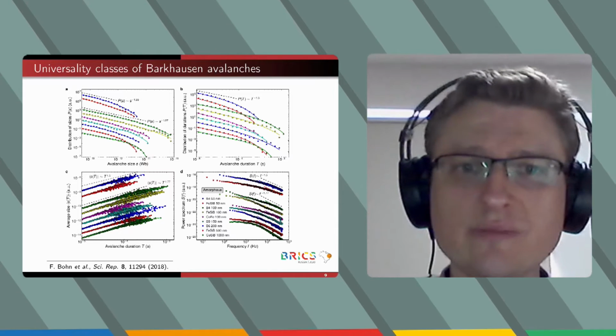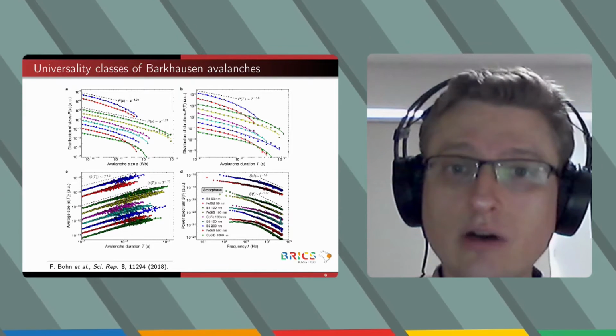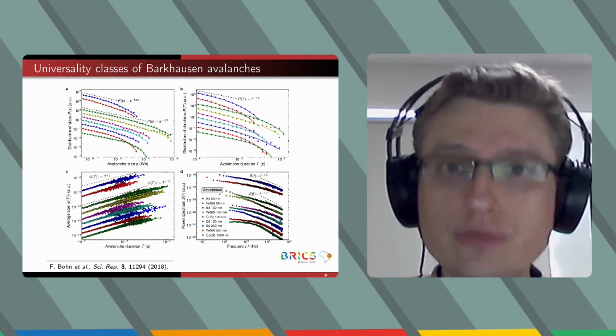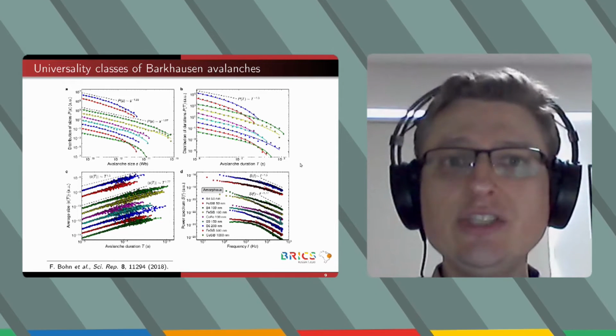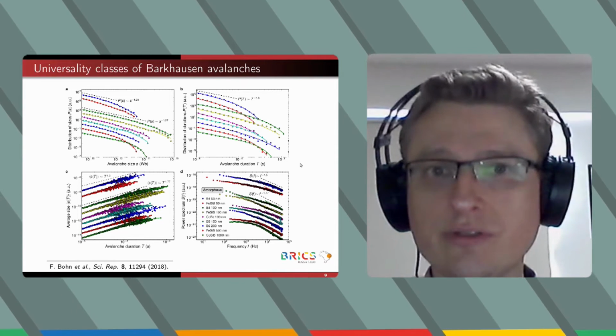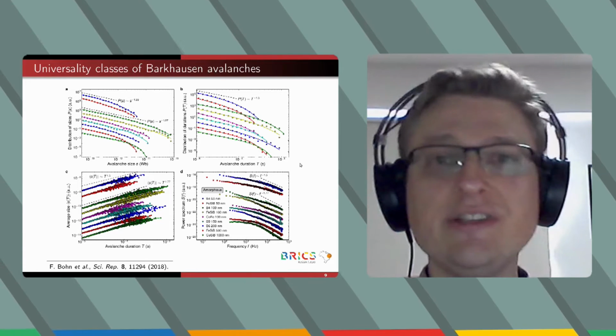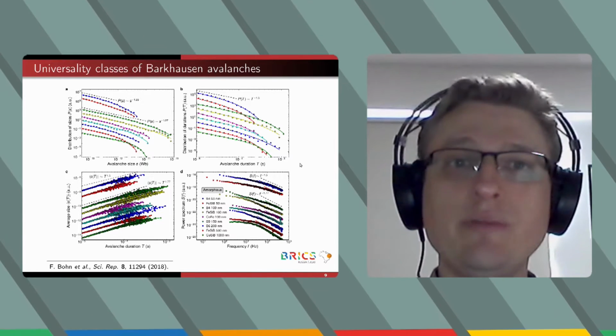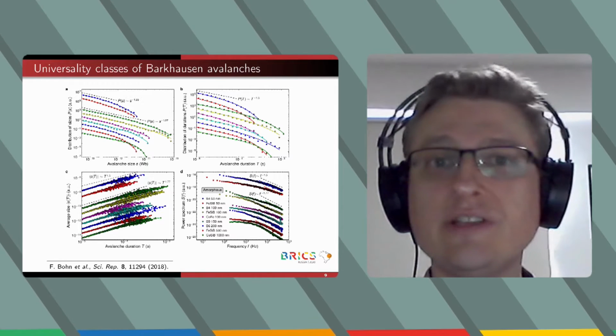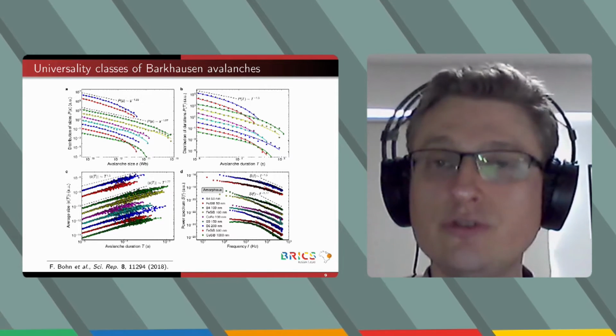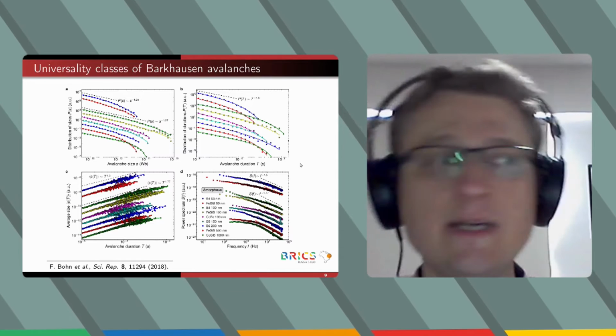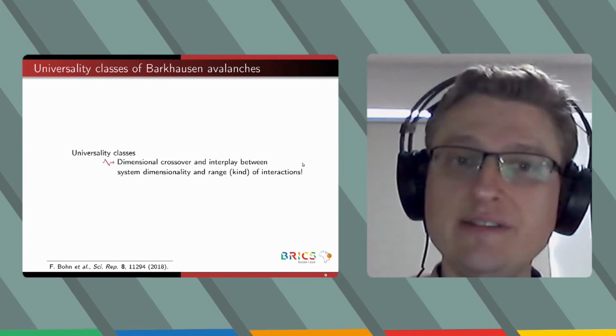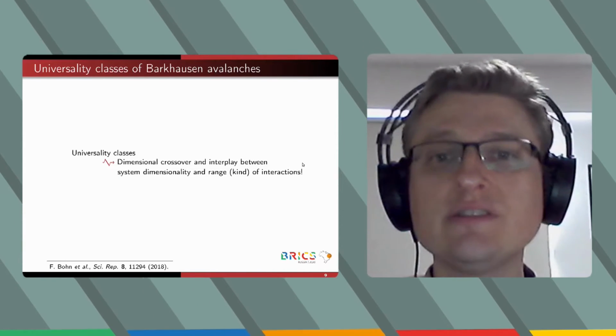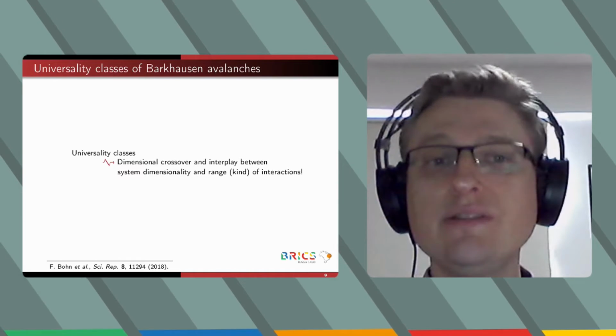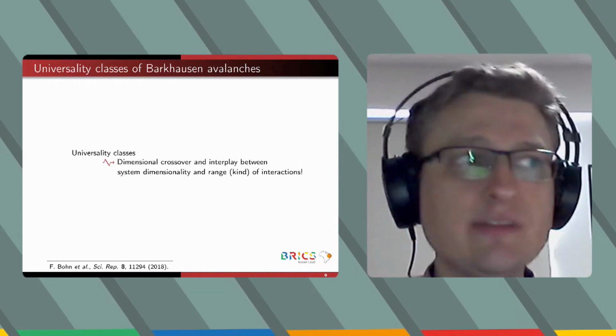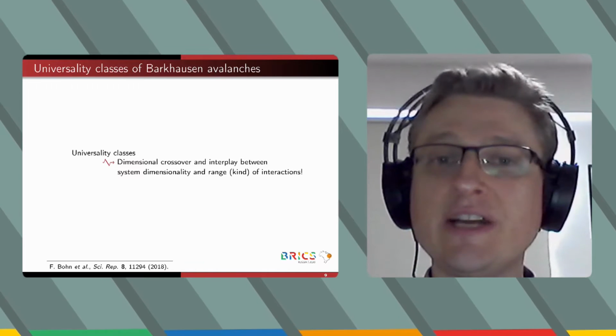For the case of amorphous materials, there are also two universality classes. In addition to the dimensional crossover, we found a change in the interaction governing the dynamics, passing from short to long-range interactions as the system goes from 3D to 2D. Thus, we identified that the key to understanding the Barkhausen statistics in films resides in the interplay between system dimensionality and range of interactions.